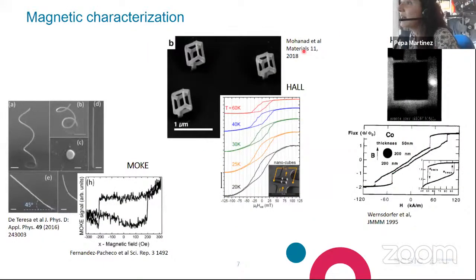In this next slide, I wanted to show you, to compare, typical hysteresis curves obtained with these three different techniques that I've mentioned: MOKE, Hall, and microSQUID magnetometry. This is a MOKE curve obtained for this iron nanowire here that you see at 45 degrees with respect to the substrate. As you can see, the noise to signal ratio is not so good, and please keep in mind that these measurements are usually obtained after integrating over many cycles.